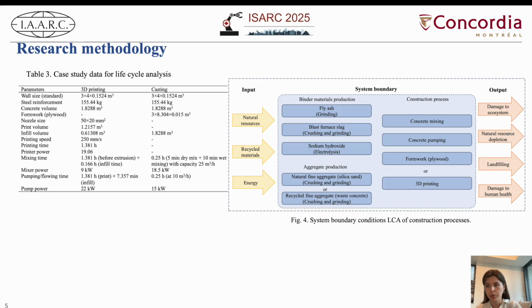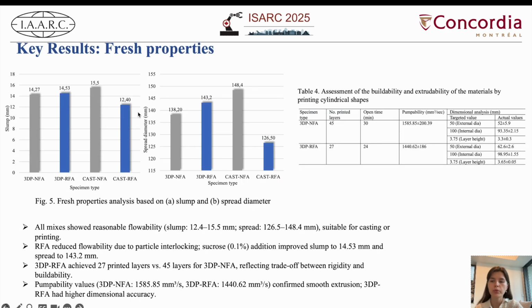In the casting process, we included the use of formwork, mixing operation, and pumping, along with the energy associated with each step. We observed that the recycled aggregate mixture for casting had the lowest slump due to the irregular shape of the recycled particles. So for 3D printing, this mixture was initially too stiff to pump, so we added a small amount of sucrose to improve its flowability.